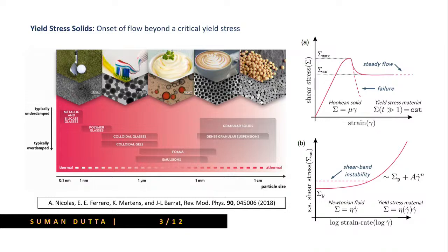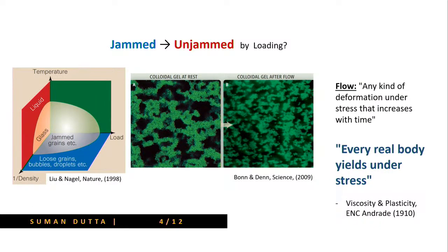So for a yield stress material, one of the criteria is that the steady stress is a constant. And as I already made clear, what we are trying to understand is this unjamming transition. This is the very famous Liu and Nagel phase diagram of jamming. It is a 3-dimensional phase diagram. On this axis we have the temperature, here we have the load, and this is 1 upon density. The questions that we are going to address are valid for T equal to 0, because we are dealing with materials that are not responsive to temperature. So these are all athermal materials, and we are at T equal to 0. That is basically the blue plane.